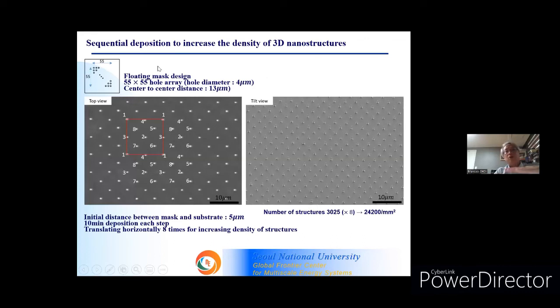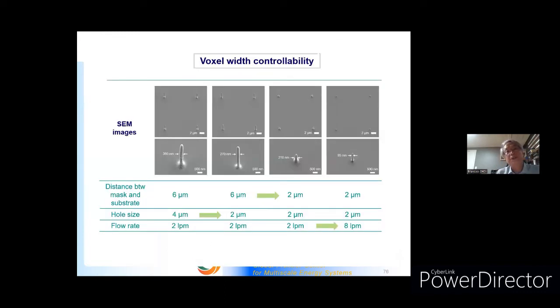Also, after you deposit one structure, you move the stage, and then you can deposit again. So one step generates around 3,000 nanostructures at the same time. If you repeat 8 times, you can make more than 20,000 nanostructures per millimeter square. So this is a parallel process. We can increase the density of the 3D nanostructures on the same substrate, or you can change material. On the same substrate, you can make different material three-dimensional nanostructures.